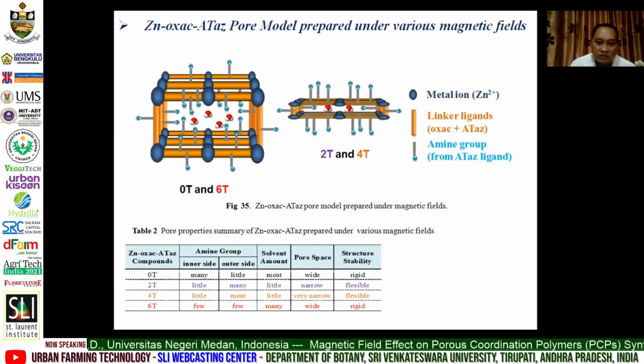And here we try to make a model of the Zn-oxac-ATaz crystal under magnetic field. We consider it based on the CO2 adsorption and also the characterization data from XRD and SEM. This is the model of Zn-oxac-ATaz for 0 Tesla and 6 Tesla. For the interaction between the amine group and the carbon dioxide, it looks like 0 Tesla and 6 Tesla have a wide pore space and rigid structure stability. But for 2 Tesla and 4 Tesla, the pore space looks narrow, and 4 Tesla may be very narrow if we observe from the adsorption data. And we consider these 2 Tesla and 4 Tesla crystals form a flexible structure.